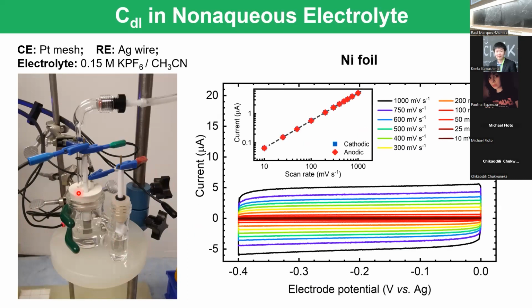These are some examples. So this is just bare nickel foil. Notice that we have an almost rectangular shape. This is what we expect to see, especially since it's a metal, so we should not expect any problems here. Notice that we're scanning from 10 millivolts per second and going up to 1 volt per second.